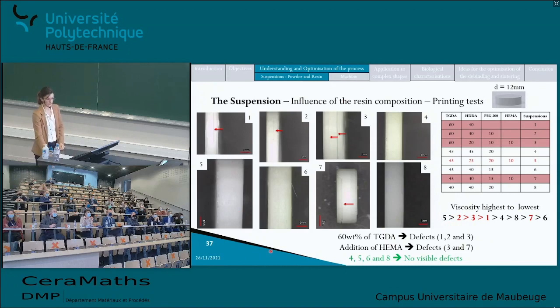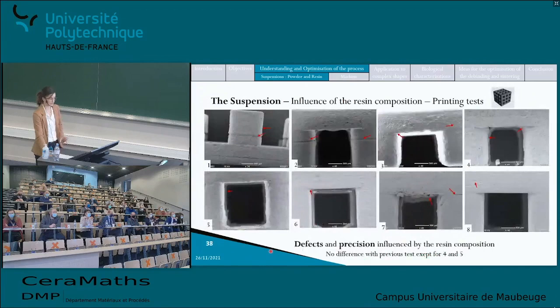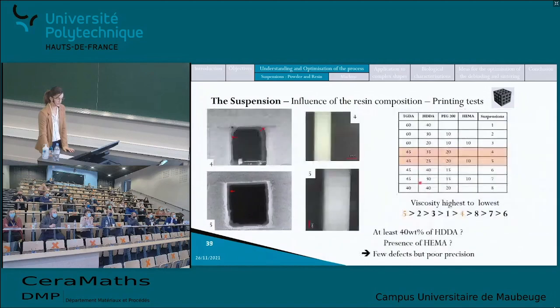Here you can see the same defects on samples 1, 2, and 3 that appeared on the pellets. So there are cracks and big delamination. Also on sample 7, there are cracks and a lot of defects. And the only difference that was observable compared to the previous test was for samples 4 and 5. Samples 4 and 5 appeared to be defectless, but here there are actually defects on the surface, and there is also a lack of precision in the structure, because this is supposed to be a square shape. So the suspension compositions 4 and 5 actually did not provide the best quality of sample.